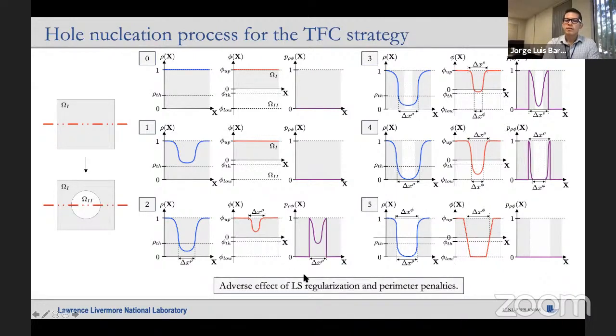Now, unfortunately, there might be some adverse effects between the components of the regularization and perimeter penalty and the new couple penalty, because, as I mentioned earlier, the regularization is trying to make you have a well-regularized level set field. With that, I mean having something that looks like this, clearly defined upper and lower bounds and a nice gradient of one. This is what you typically want in a level set field to have a smooth problem. But your level set regularization, once it sees this dip start evolving, may want to make it move up to what you had before.